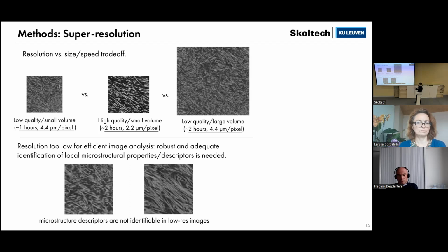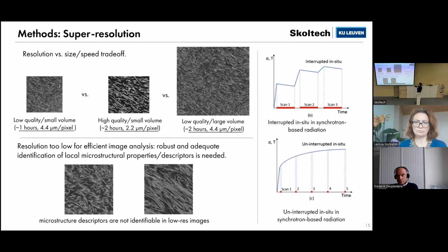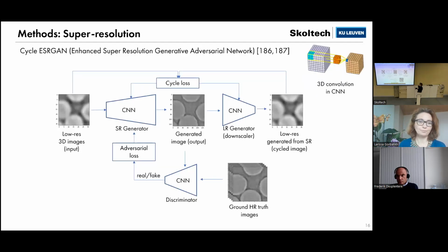And sometimes we cannot increase the time of the scanning process. For example, here you can see an interrupted in situ test in synchrotron-based radiation, and you can see how it affects our mechanical testing results. But in an uninterrupted test, the time of scanning is much lower, and we cannot increase the scanning time. This is why we cannot always have high quality images, and why we need an algorithm to overcome this.